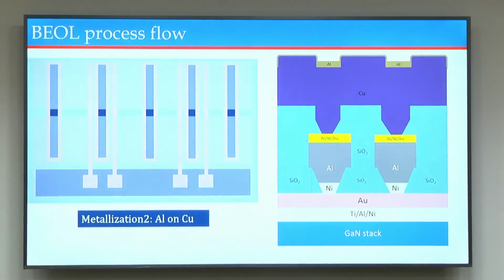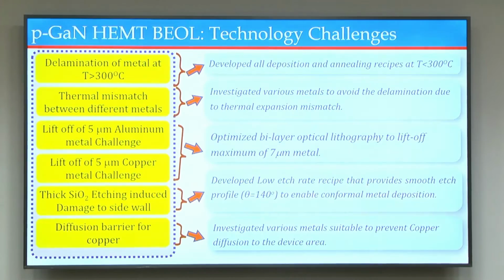So we have developed the entire back end of the line. As I said, there are all these challenges. For example, if you have these thick metals and if you do any high temperature process, in this case I am talking about more than 300 degrees C, you have delamination kind of issues, right. These are thick metals, so there is a lot of stress also between the metal layers, right. Then there is thermal mismatch between different metals, so you have to choose the right metals which have better adhesion to each other and also less thermal mismatch with each other.